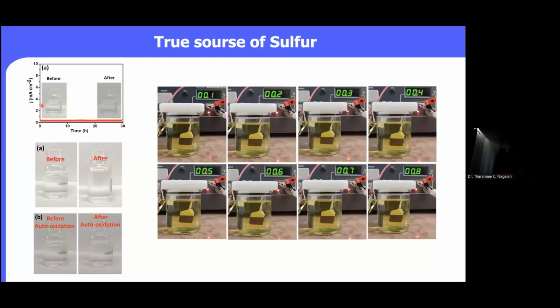But you can see that we do not see any changes in the color. That means there is no polysulfide yellow color in the solution. And to further confirm, we have done the acid treatment, but we did not see any precipitation. That means there is no polysulfide produced due to the molybdenum sulfide in this case.